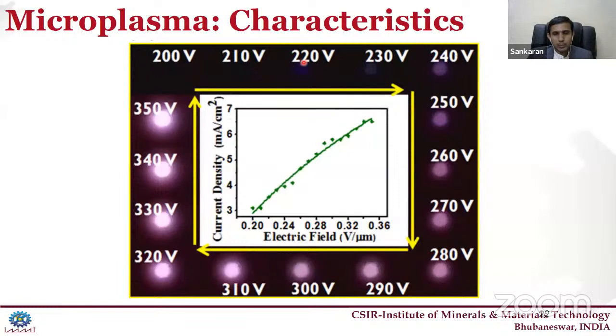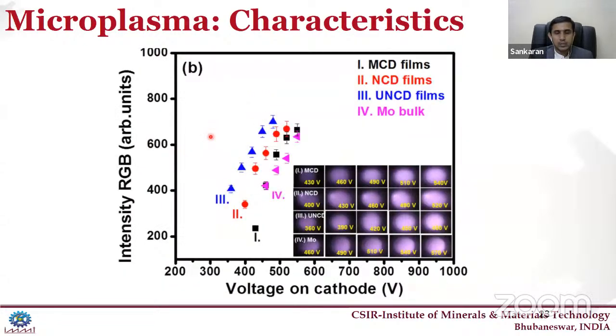This is a particular diamond material I'm talking about now, but we'll discuss more different materials and how we are going with the diamond thin film. We are calculating the breakdown voltage where the plasma emits. We also calculate the breakdown voltage from the current density versus the electric field curve, and the current density at a particular applied field. Like at 0.32 volt per micrometer, the current density we have observed is nearly 5.8 milliampere per centimeter square. Another parameter is the RGB values, the intensity of the RGB values.